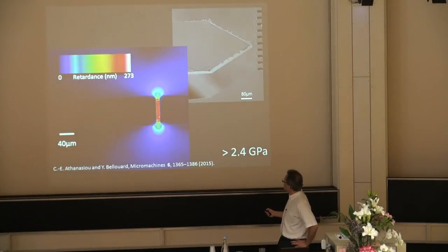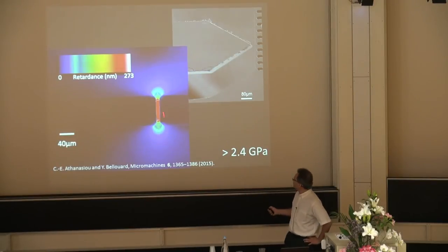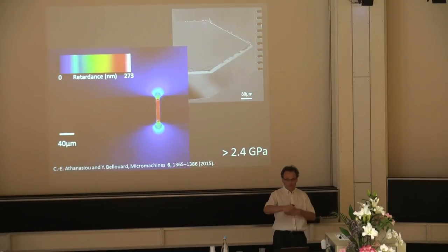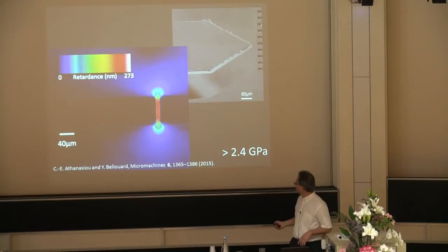So for instance, here you see that the test beam is 8 microns wide, and a bit more than 40 microns in length. Very, very small. And then we loaded it, for instance, here to 2.4 gigapascal, just to observe how it is reacting. So this is a real image, looking at the stress in there.